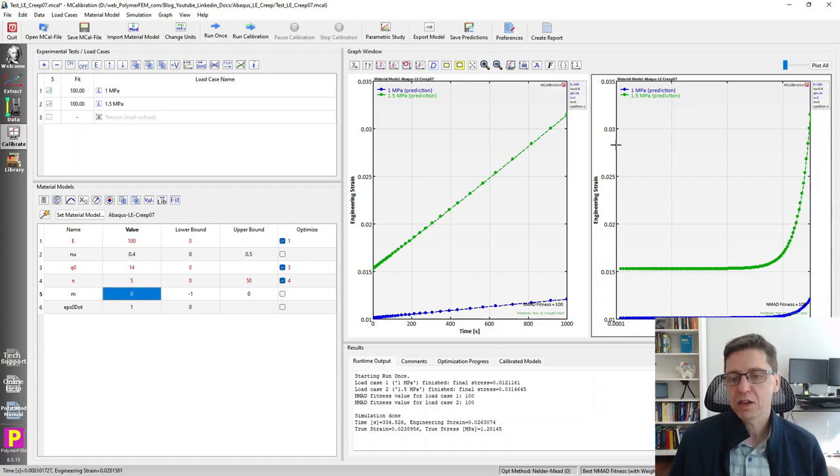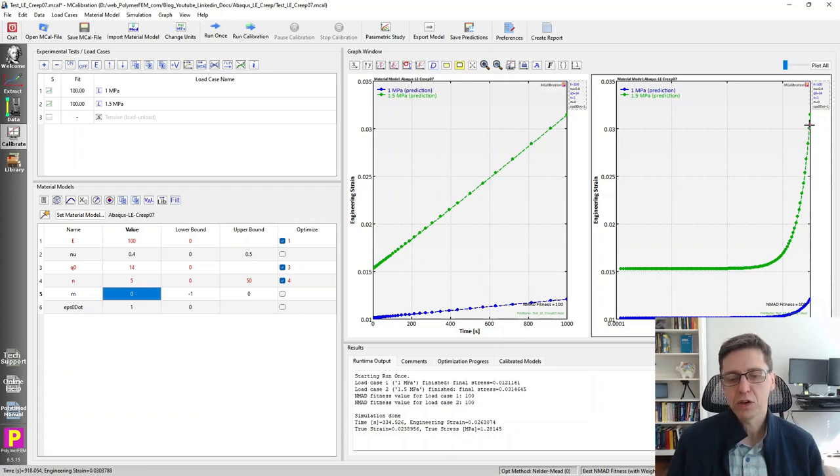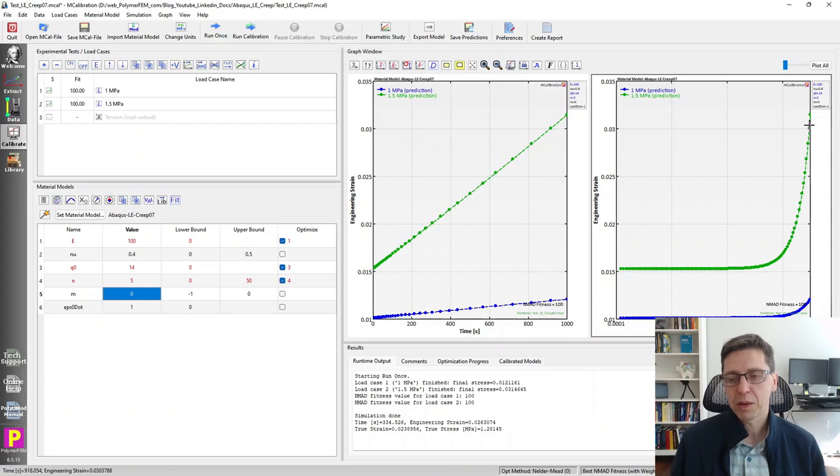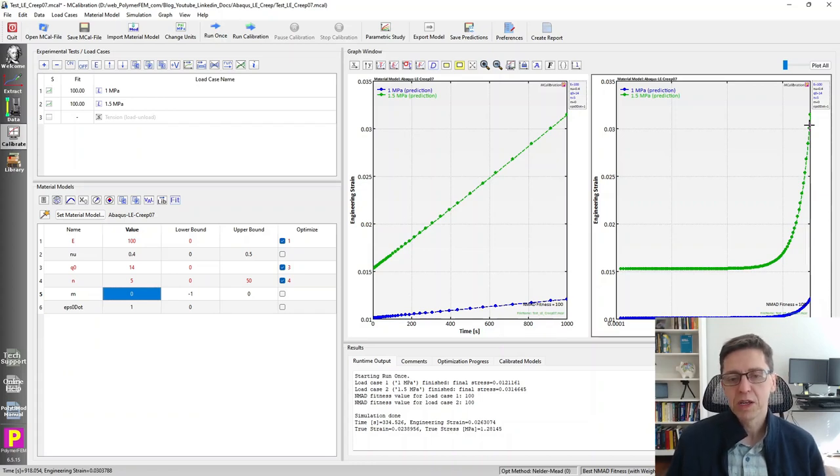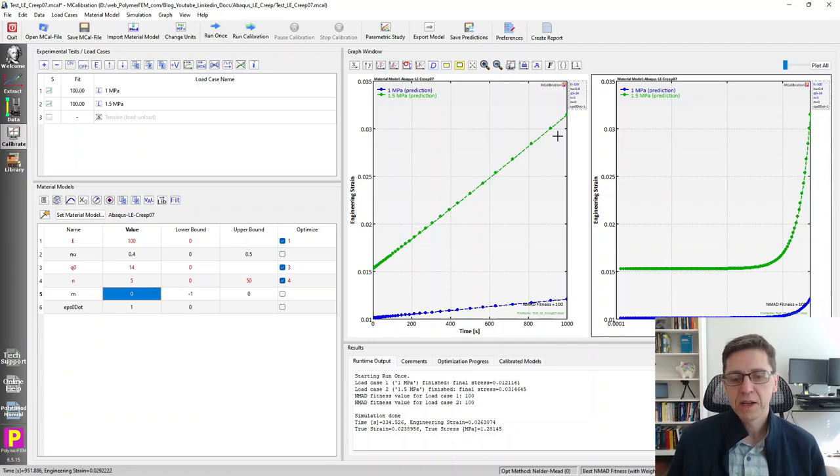And here is that on the figure to the right. We're going to do time on the x-axis, on the y-axis engineering strain, but I want the x-axis to be logarithmic, so I'm going to switch that over like this. So here we can see that if M is equal to zero, the creep strain is linearly increasing with time. Of course, that's just the equation for a given constant value of strain. In this case, the strain doesn't matter because M is zero, we get this response. But if you plot strain, creep strain as a function of logarithmic time, we'll see this very interesting effect, it really accelerated a lot at large strains. This is sometimes happening in polymers, but not always. And this is certainly a concern due to this simple response of it.